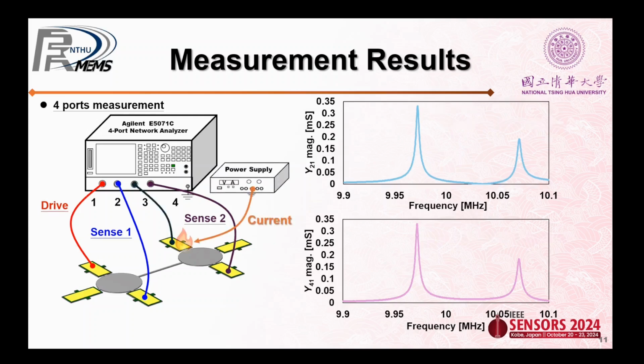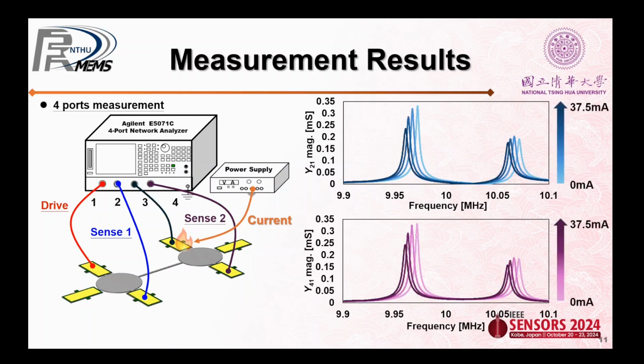The next part involved verifying the mode localization phenomenon. I used the power supply to introduce a DC current, and it can be observed that after introducing the target signal, both the amplitude and the frequency change. The frequencies are all shifted to the left because the temperature coefficient of frequency, TCF, of the device is negative.